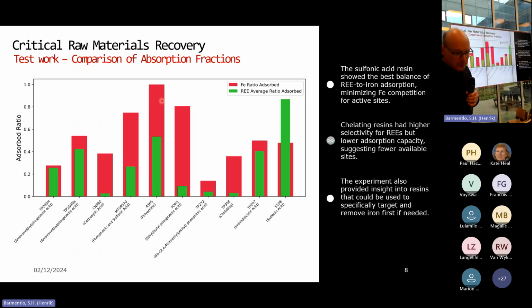It's fine. So what we see is that this S108, which is the sulfonic acid resin, we found had a really good rare earth element absorption and fairly poor iron absorption. And that's what you want from these resins. You want to selectively strip out the rare earths and leave your iron behind. So we tested all of these different things. For instance, this POH1 was quite good at iron removal, but not very good at rare earth element removal. So we started with testing all of these things.